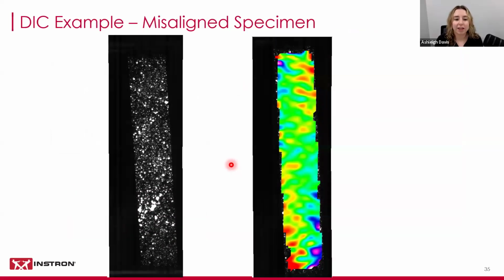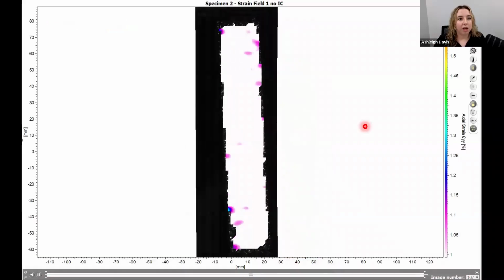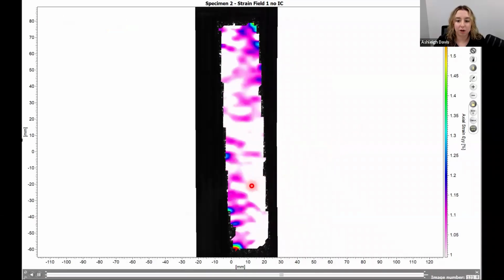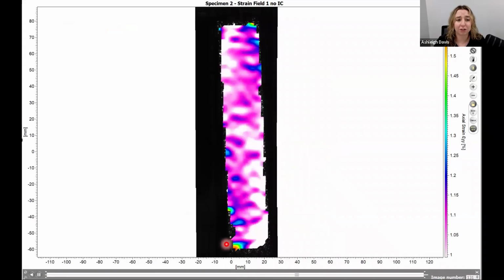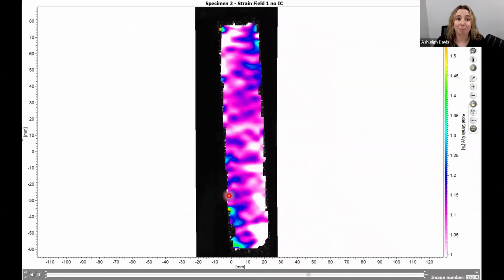So we have an example coupon we tested last year for our strain webinar, where we purposefully misaligned the coupon in the grips, and we used our video extensometer and digital image correlation to map the strain map or the stress map during tests. So in the next slide, we have the video of the test actually occurring. And we can see the map changing over the course of the test, with higher concentrations of stress actually in that lower left corner and that upper right corner.